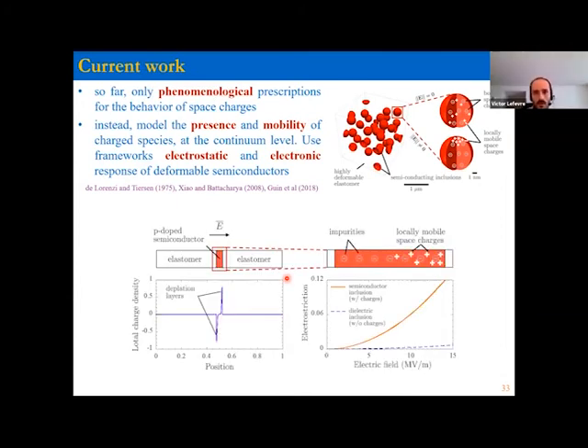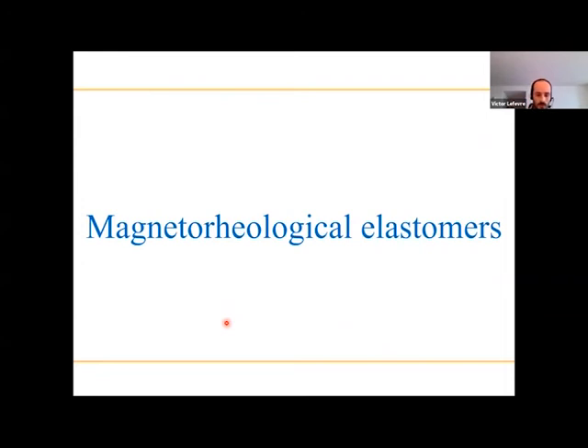This is just a 1D preliminary result. And you can see that, again, once you have space charges, you have a significant enhancement in the electrostriction. It's a completely different problem. It's another set of equations to deal with. You have a lot of difficulties and challenges to deal with the numerics, because you have these very sharp layers where the space charges concentrate. It's a completely different problem, and that's what we're looking at. All right, so that was all for dielectric elastomer composites.